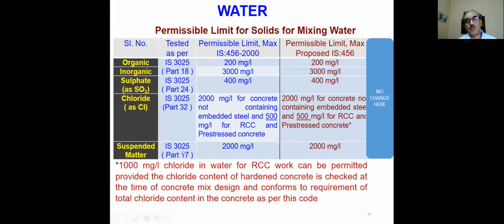And for PSC, up to 1000 is permitted. Earlier it was 1000, which was brought down to 500 later on because the chloride limit in cements was increased. But many cements have low chlorides, so what we are saying is if the total chlorides are within limits and it is tested specifically for the hardened concrete also, then up to 1000 milligram per liter may be permitted.